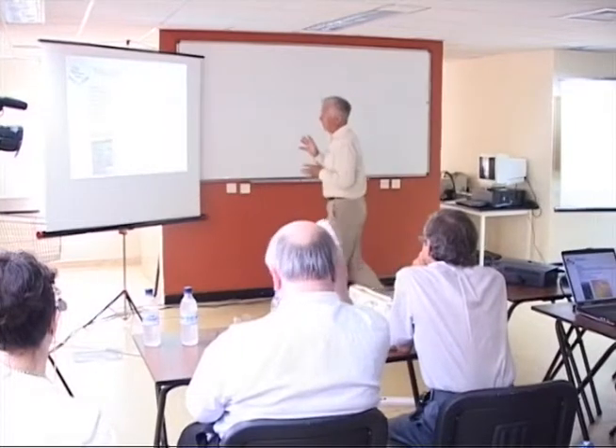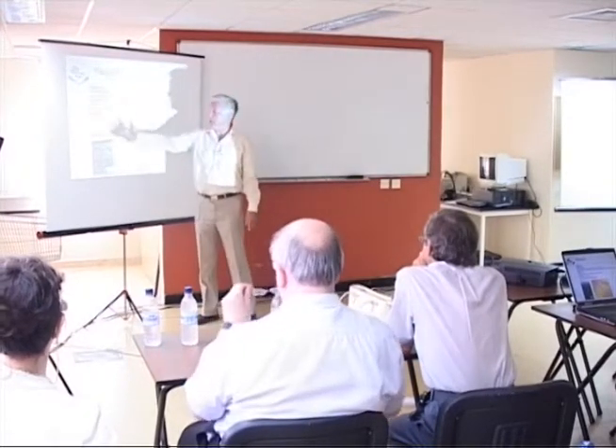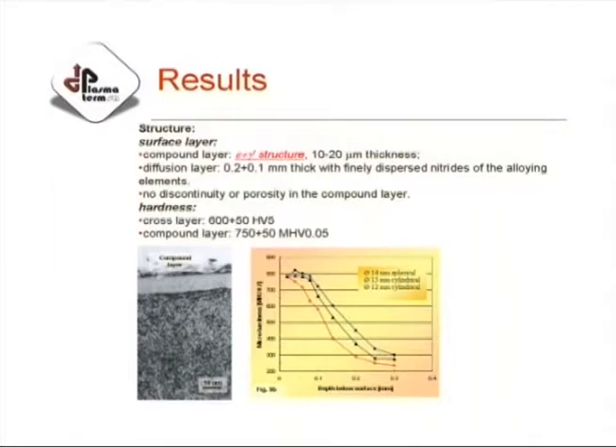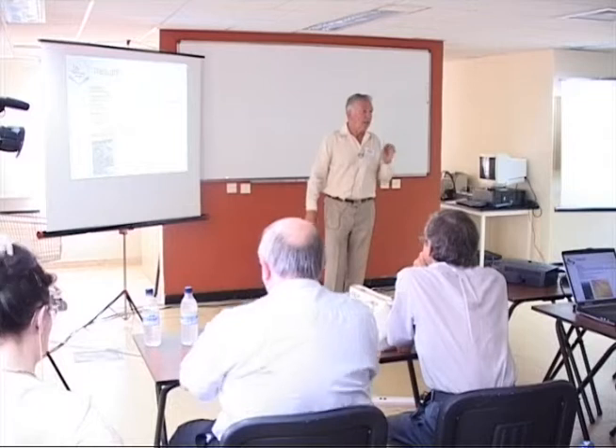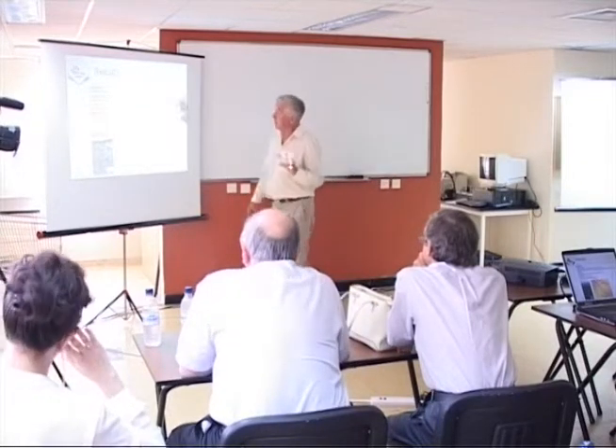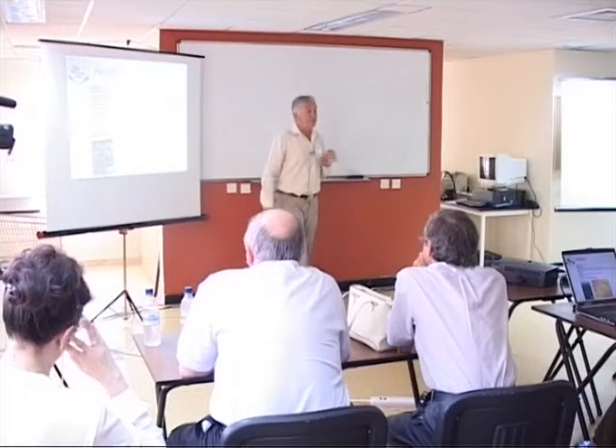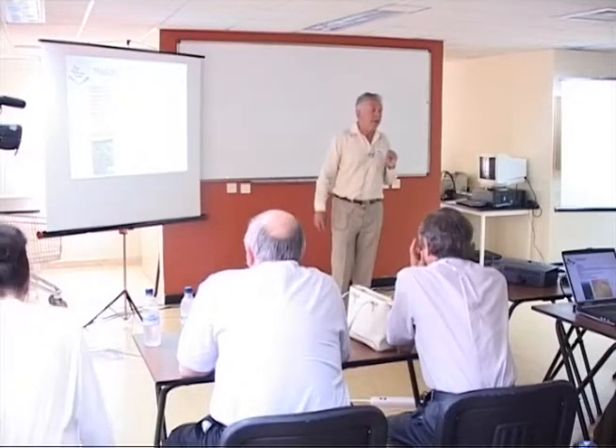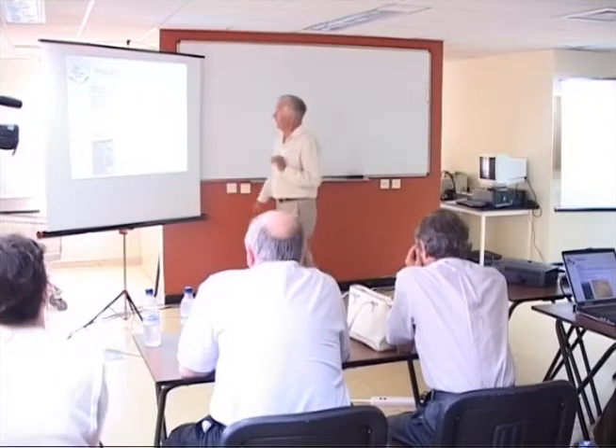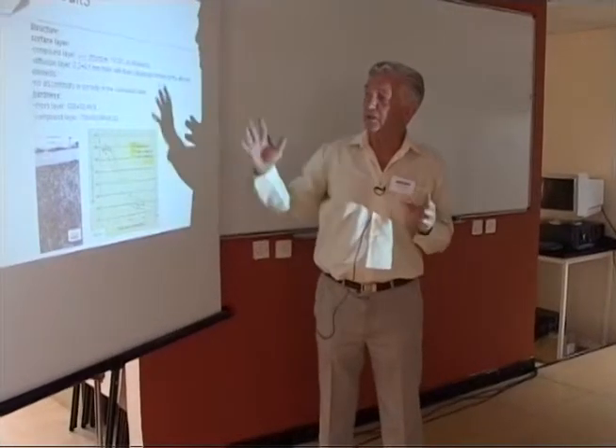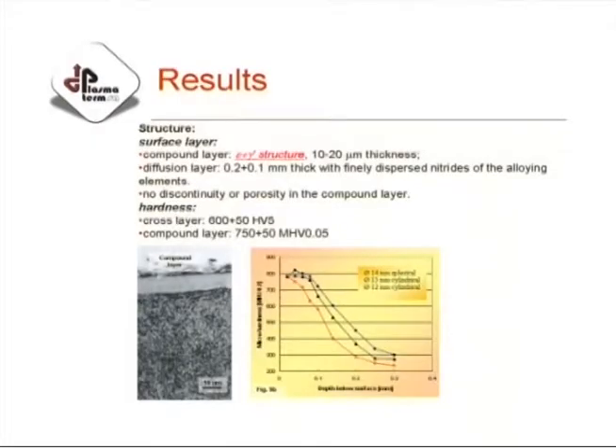Well, this is a typical structure of the layer where you have a compound layer of 10 to 20, but normally around 15 microns, and mostly this compound layer is an epsilon type layer, so not pure epsilon, it has gamma dash as well, but basically epsilon, because according to our experience, the best results in sliding friction we can get from epsilon type layers. Then we have a diffusion layer which is roughly between 0 to 0.3 millimeters, and we have no discontinuity or porosity in the compound layer. It's clear, you can see it clearly.